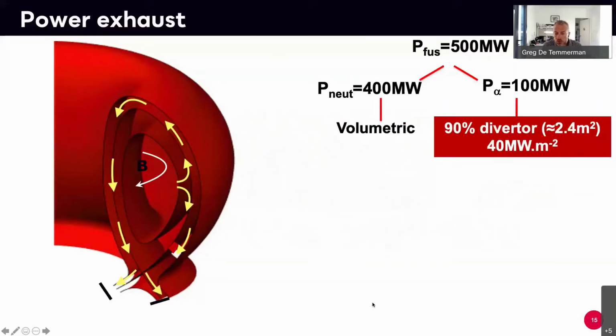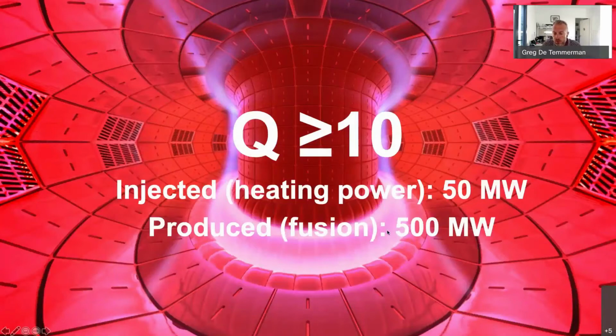So just to give you some numbers. The aim of ITER is to produce 500 megawatts of fusion power. So this is thermal power. ITER will not generate electricity. It only generates heat, and we have cooling around, so we basically dump that heat into water. But we don't do anything out of it. And then we inject, the aim is to inject about 50 megawatts, so you have a ratio of about 10 between both values.